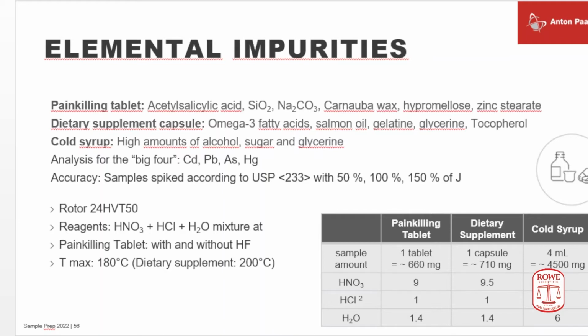Look at the table to the lower right. Depending on the nature of the sample, the reaction chemistry was varied. So for the pain-killing tablet it is a straightforward nitric acid, a little hydrochloric, and a little bit of water. Why water? In this amount of water, we added a spike solution, because what we did for the pharmaceutical samples was spike tests. Spiking the sample and checking the recovery after the digest to see if the digest was complete and if you did not lose any type of analyte.